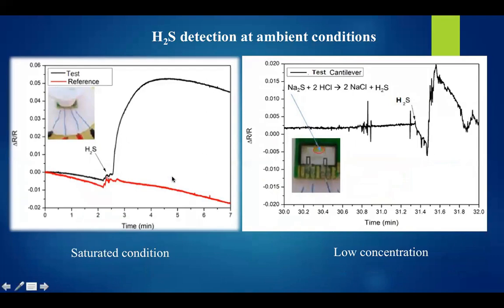In case of H2S, when we expose the test and reference cantilevers to H2S, one can see that the material is highly selective to H2S, and the test cantilever showed a transient change in the resistance with time. As we have a closed cap scenario here, we have a saturated H2S gas condition, and we did not see any recovery, which indicates that the H2S gas is chemisorbed, and chemisorption is the major mode of interaction here.